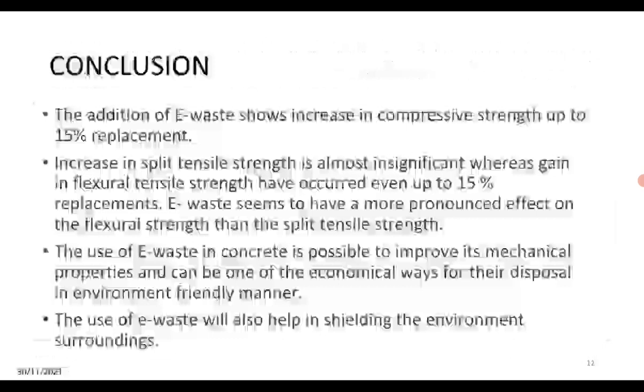In conclusion, the addition of e-waste shows an increase in compressive strength up to 15% replacement. The increase in split tensile strength is almost insignificant, whereas a gain in flexural tensile strength occurs even up to 15% replacement. E-waste appears to have a more profound effect on flexural strength than on split tensile strength. The use of e-waste in concrete can improve its mechanical properties and represents an economical and environment-friendly method of disposal. It will also help in shielding the surrounding environment.